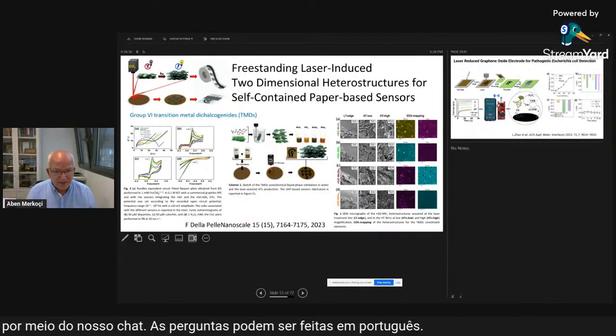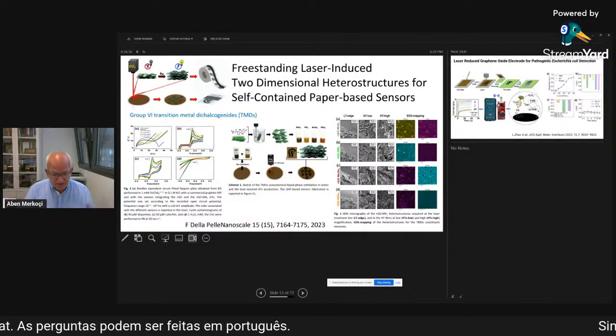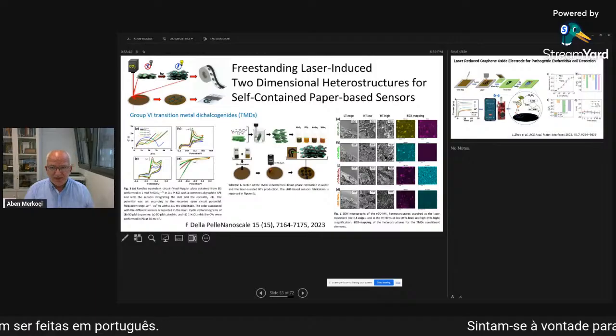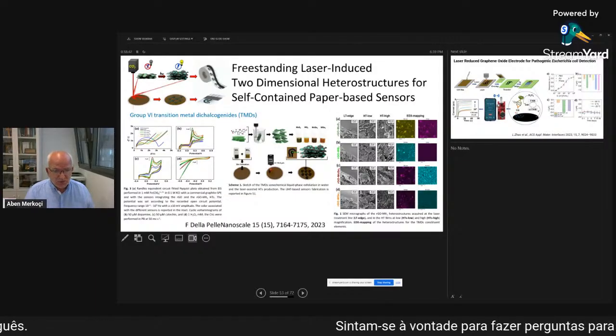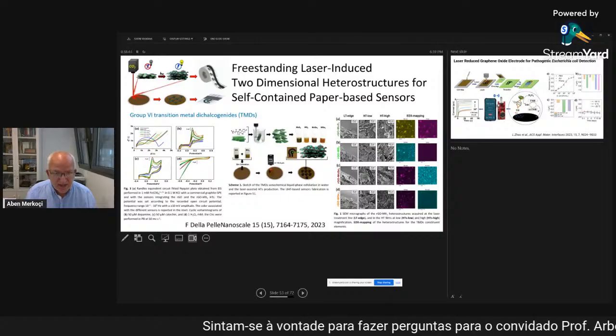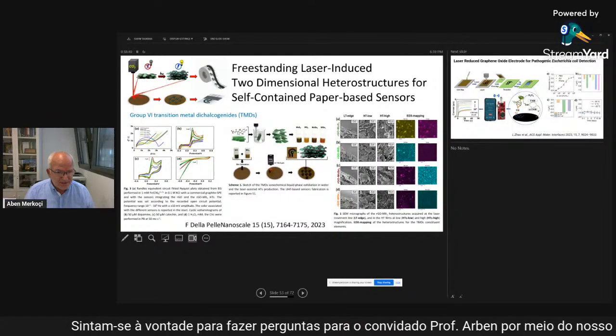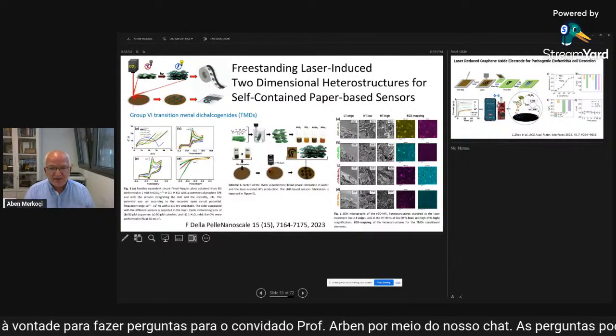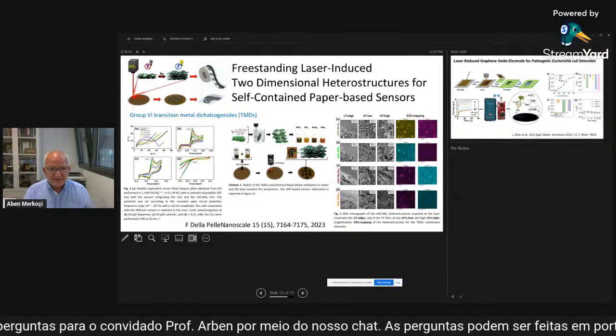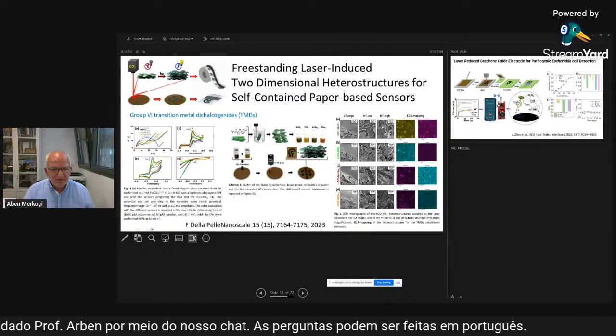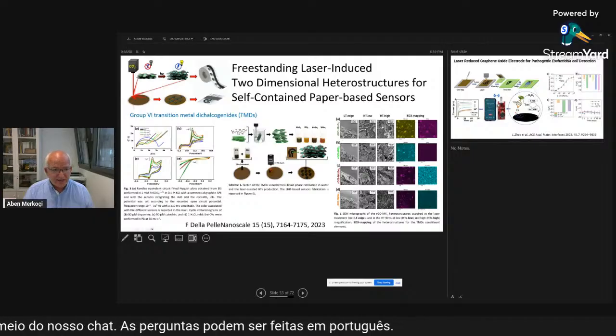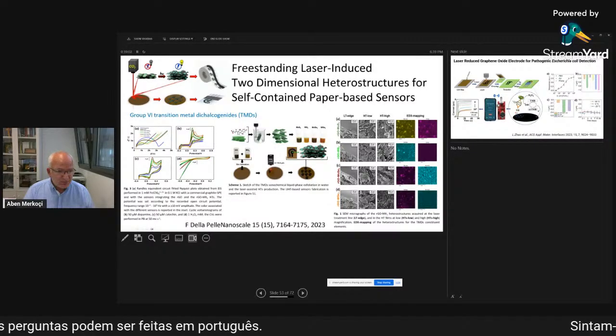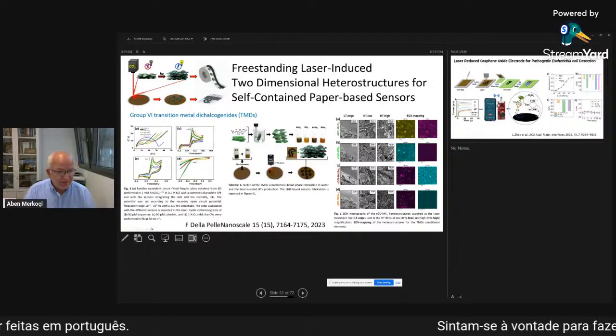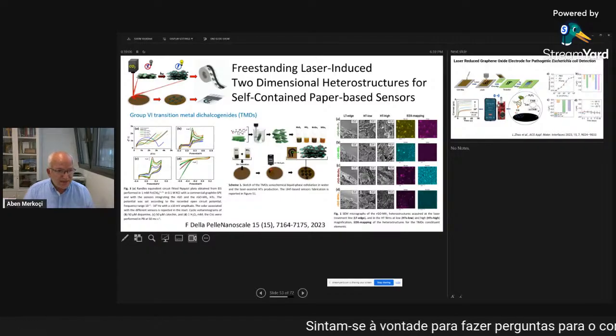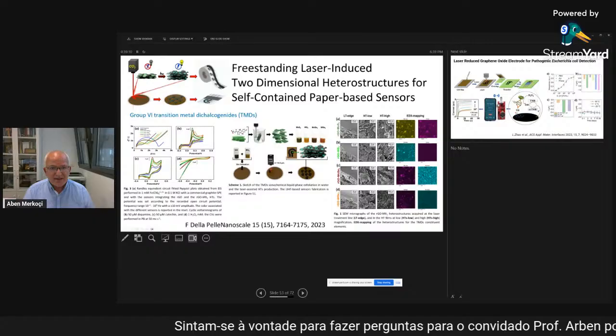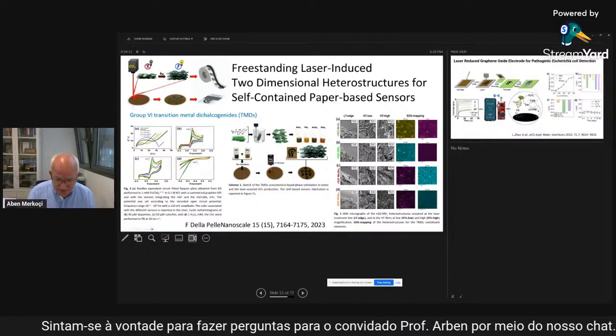For example, here is another example in which we included some two-dimensional structures. So we combine graphene with these TMDs to have a synergy between graphene and these materials, with the interest of improving the electron transfer and having these sensors produced even onto paper for electrochemical applications. You see here, for example, the improvement of the system from graphene to reduced graphene oxide, including these two-dimensional heterostructures.